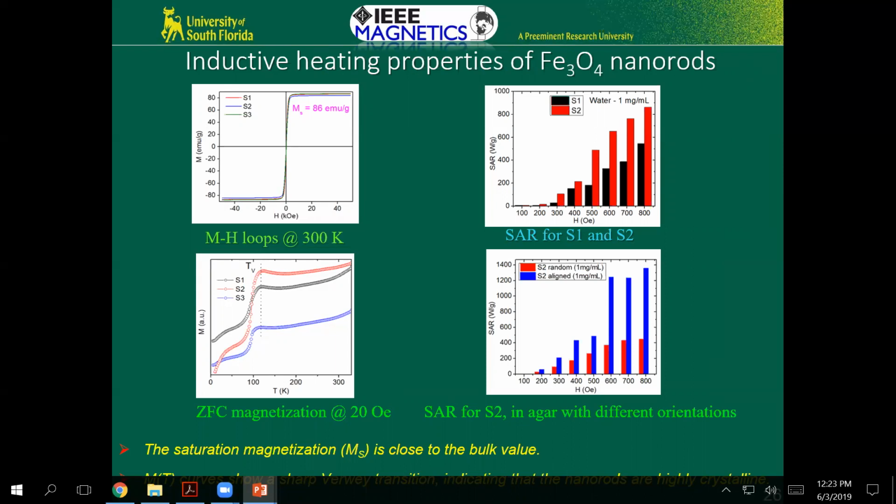In magnetite, you can also do a quality check, whether your magnetite particle is high quality or not. It turns out that Fe3O4 magnetite has a celebrated metal insulator transition. At low temperature, 120 Kelvin, because of a first order phase transition, it becomes from a metal to a really good insulator, a huge metal insulator transition.